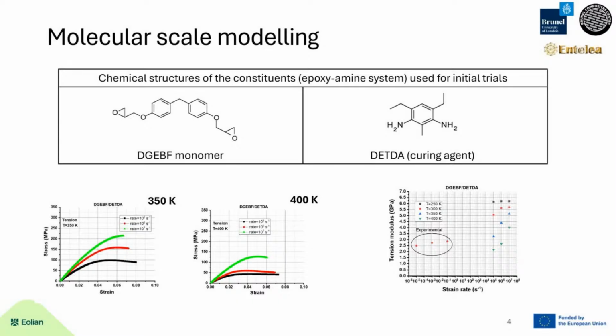Just as an example here, I have not included the results of the vitrimers yet, but I have included an example thermoset that we studied. It's just a thermoset epoxy amine system. These are the chemical formulations that we used. On the bottom left, as you can see, we could extract the stress strain curves of this polymer at different temperatures, at different strain rates. And on the bottom right, this is the modulus which is plotted against the strain rate. All the points on the right side are obtained from the atomistic scale simulations that were performed.